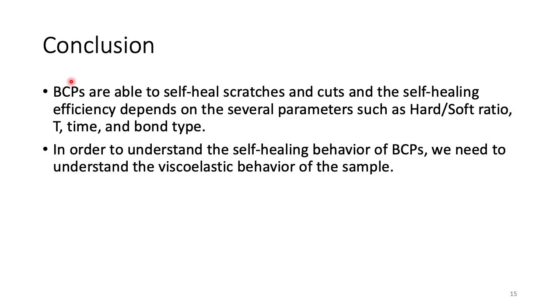In conclusion, block copolymers are able to self-heal scratches and cuts, and the self-healing efficiency depends on several parameters such as hard versus soft ratio, time, temperature, and also bond type. And in order to understand the self-healing behavior of block copolymers, we need to understand the viscoelastic behavior of the sample. And thank you for listening.